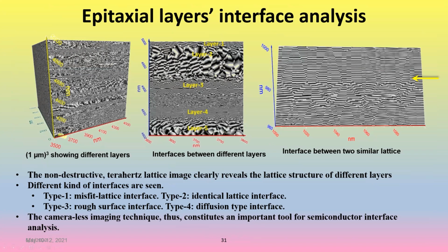On the upper right, you have this line that you can see between 2 different almost identical lattices, but the interface line is visible. So this is a very good interface on the upper right. On the left, on the middle, the interfaces are characterized as the layer 1 is the misfit between layer 1 and layer 2, misfit lattice interface, and so on and so forth.